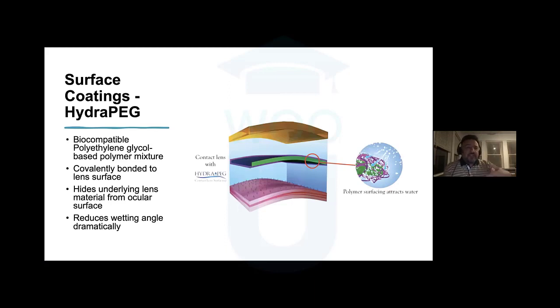The next step in the process of getting that lens to wet better, once we've cleaned it well, once we've plasma treated it to get rid of imperfections, would be to coat it with something that can significantly alter the wettability of the surface, that can help with the free energy of the lens to allow that liquid to be grabbed and spread out over the surface more broadly. And so a coating like HydraPeg, a polyethylene glycol based polymer mixture, which is covalently bonded to the lens surface after it's plasma treated to remove imperfections and to expose as much of the free polymer as possible, then covalently bonding this polyethylene glycol based mixture to the surface, then forms a shield around that lens material, and again allows the liquid of the tears to spread more rapidly and more readily over the surface. And it does reduce wetting angle dramatically.